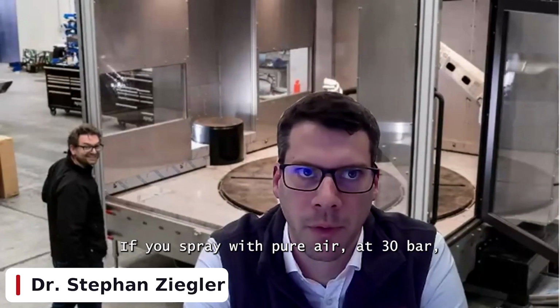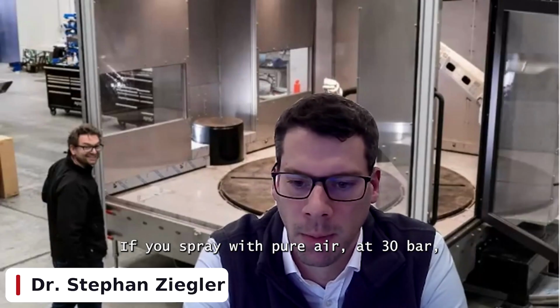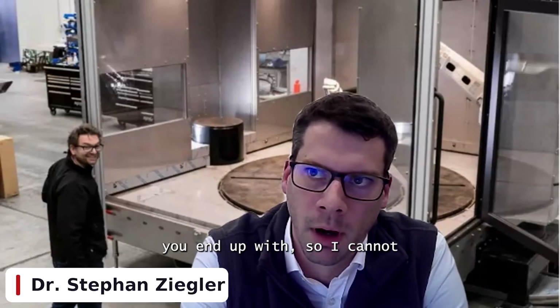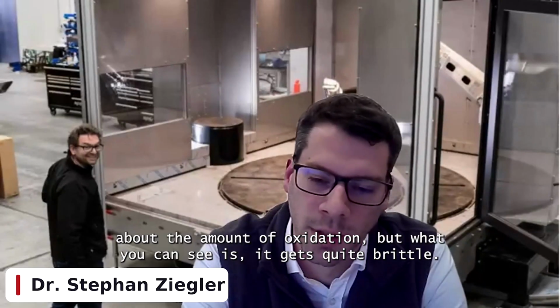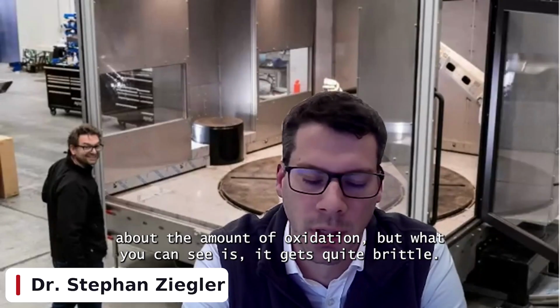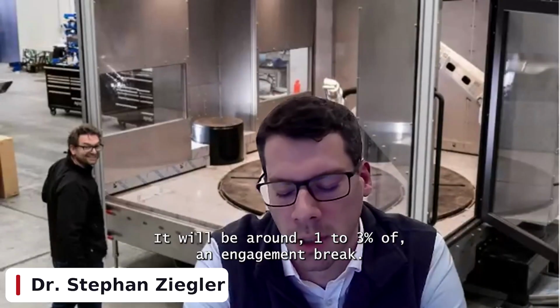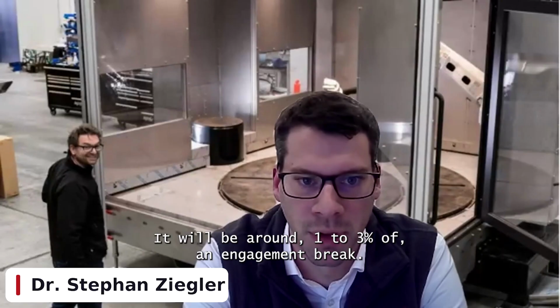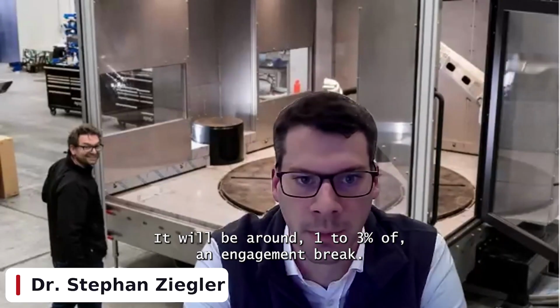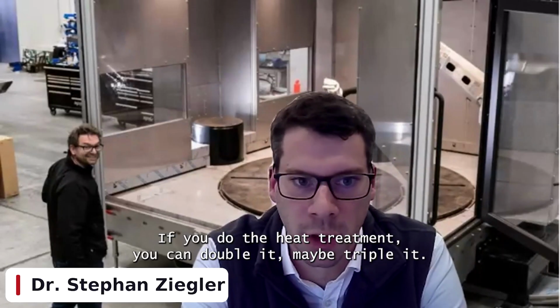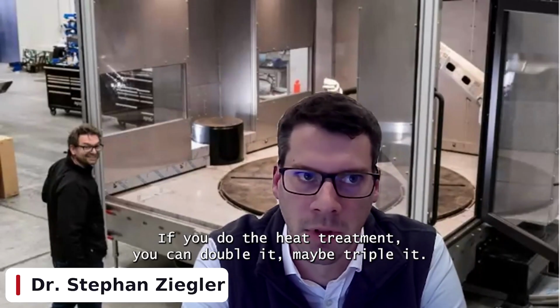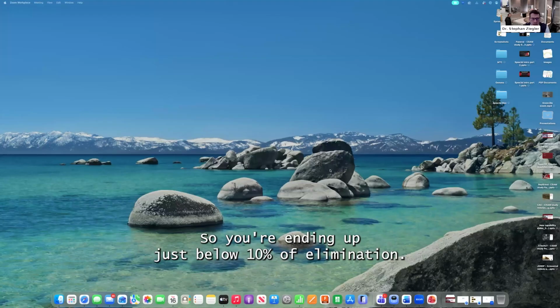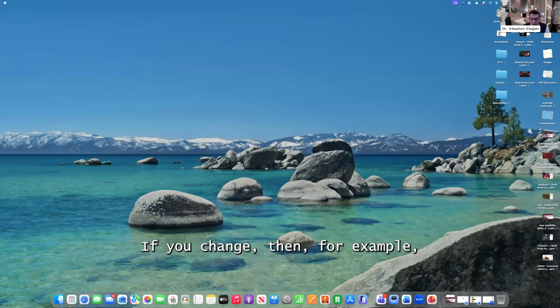If you spray it with pure air at 30 bar, you end up with, so I'm not sure about the amount of oxidation, but what you can see is it gets quite brittle. It will be around 1 to 3% of elongation at break. If you do the heat treatment, you can double it, maybe triple it. So you're ending up just below 10% of elongation.